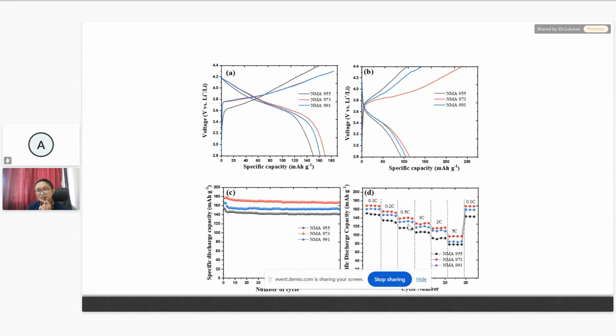In the curve of B, this is the curve after several cycles, or maybe no, this is at 1C. Previously at 0.1C we have the discharge capacity. The highest capacity belongs to NMA 973 with around 170 milliampere hour per gram, and then we increase the current density, shown in picture B, and the voltage window decreases from the curve because of the effect of the high current.